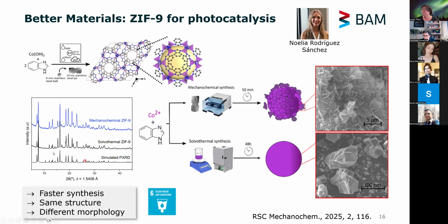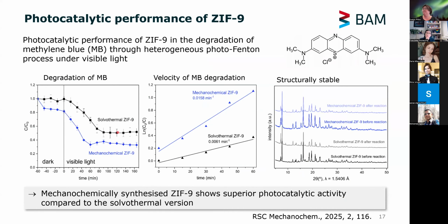Just here to see, what we usually take is X-ray diffraction, of course, to show that we have similar structures. And you can see, okay, there's a bit of an amorphous content maybe available, but the patterns are quite similar. So, and if we then use them for photocatalytic testing, you can see here that is something we usually try in the first place, degradation of methylene blue in a so-called heterogeneous photo-Fenton process.